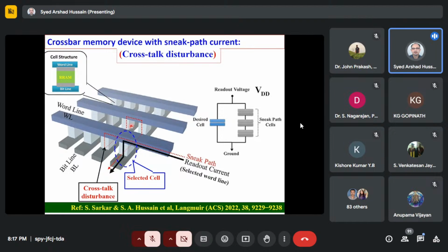Okay, in real practical applications, there is not a single cell, because there will be a number of cells in a crossbar array. Okay, so say this is a cell, you see each of these is a cell, so a number of cells. Say in this cell a zero is stored, say it is in the high resistance state. So for reading this state, what you have to do is apply some bias, say on the read line or something like that. Then you have to measure the resistance state, that means the current across the device. So if it is in the zero state, the high resistance, then if you measure the conductivity from here, it is expected that across this cell there will be hardly any conduction.